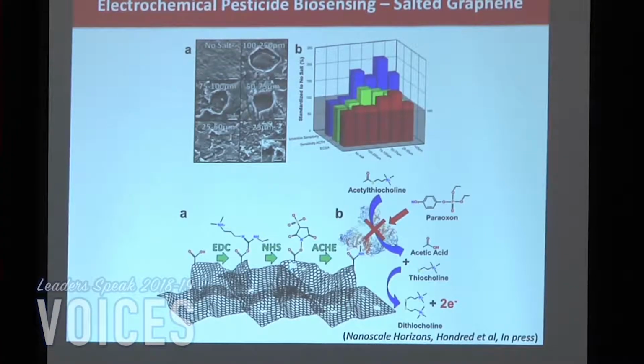One of the ways that we did that was introduce a new technique into the manufacturing of these electrodes. In this case, we took salt, a porogen, and put it into the ink itself, and then when we laser treated it, the salt would break open and leave the surface of that graphene, but it would leave behind these big craters on the micron scale. They're not so big, I guess. Nothing is really big in what I'm doing.